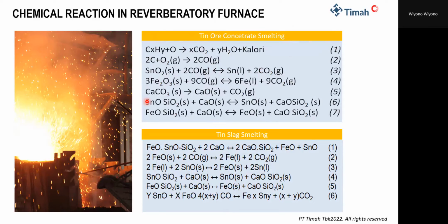And the third reaction is slag making. Slag making starts with the decomposition reaction of limestone. The limestone will decompose into CaO and CO2. The CaO will break the bonding between SnO and SiO2.